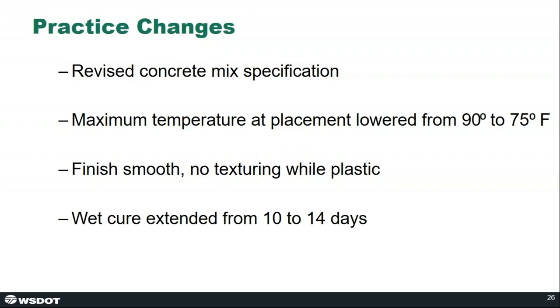This delays the onset of drying shrinkage by extending this cure, which allows the concrete to gain strength prior to the bulk of the shrinkage occurring. And in general, a longer cure is good to realize all of the good properties that lead to a durable concrete, like permeability. So this spec change has an impact. It lengthens out our schedules and comes with a cost. But given the importance of our bridge decks, this is a delay we're willing to pay for.